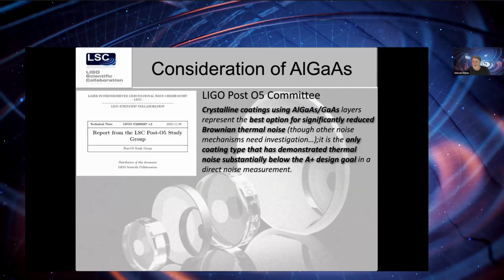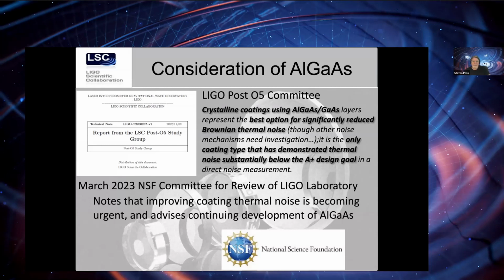And in fact, there is no amorphous coating that comes even close to the low thermal noise that's provided by crystalline coatings. And then while I don't have a direct quote from it, LIGO really recently underwent a review by the NSF, and they specifically called out that we need a great deal of improvement in coating thermal noise, that the situation is becoming urgent, and they advised us to continue the development of AlGaAs as the best candidate to solve that problem.